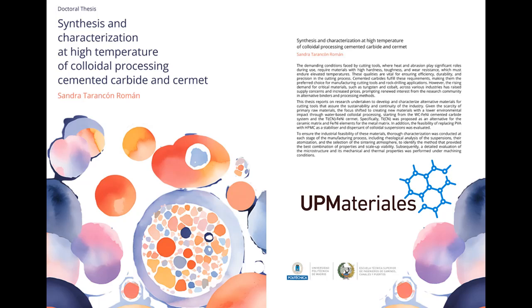What were the key findings when they compared the effects of those different sintering atmospheres? They looked at things like hardness, which is shown in figure 4.12, and the amount of porosity left in the final material. They found that sintering in the hydrogenated nitrogen atmosphere resulted in lower hardness, and they discovered that some unwanted chemical reactions had occurred, which explains the reduced hardness.